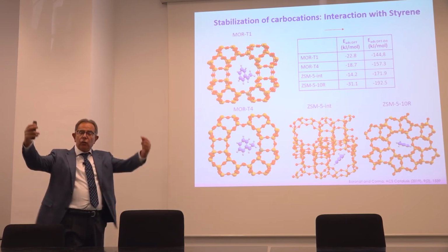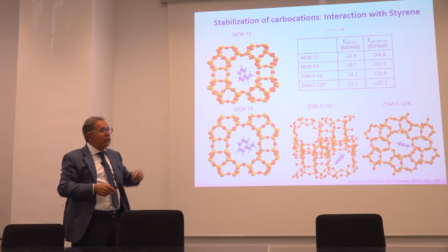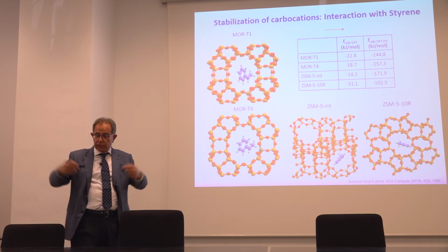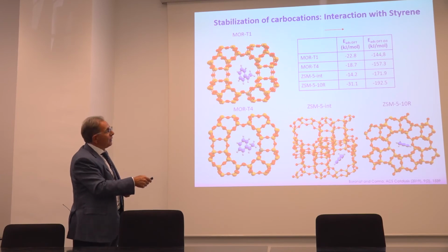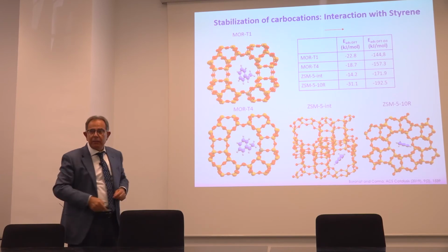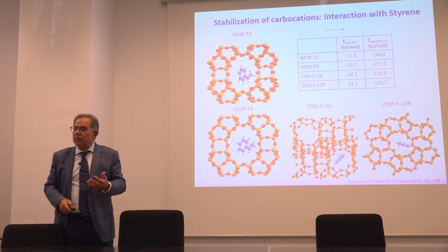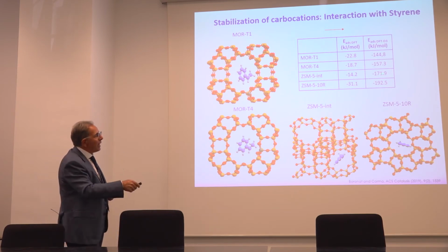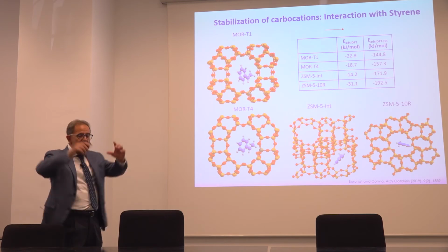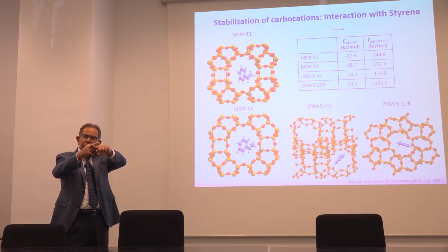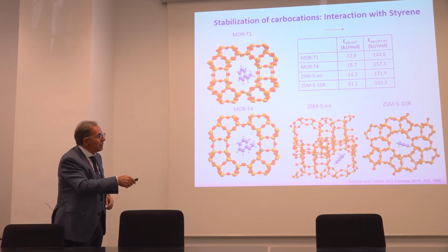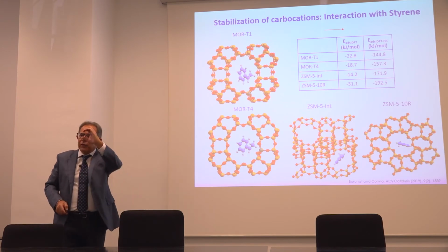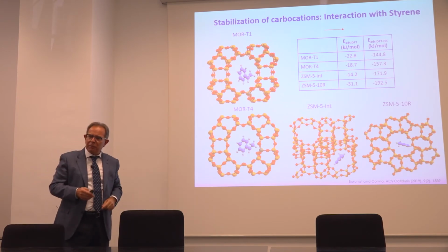When now you start to consider, by calculating the dispersion forces, the interactions with the walls, look at the big jump in stabilization. You stabilize those much more. And when you come now into the zeolite ZSM5, in where you have the crossing points and in where you have the channels with different void space, you see that the stabilization is different. Stabilization is larger when you go into the channel instead of the void space.